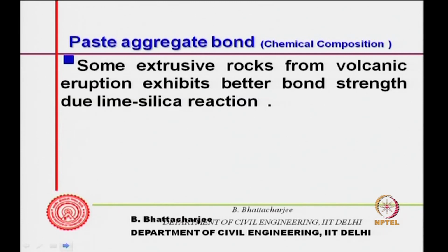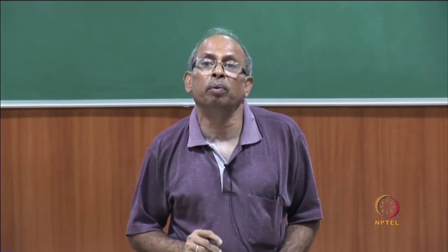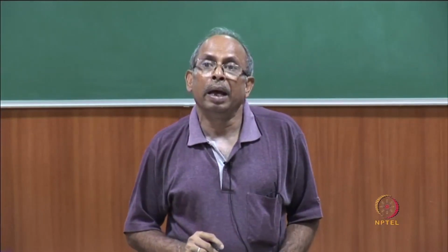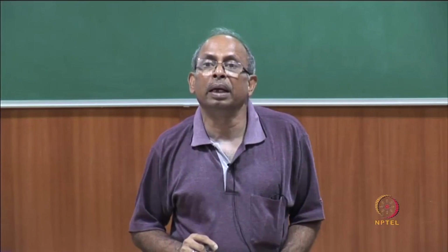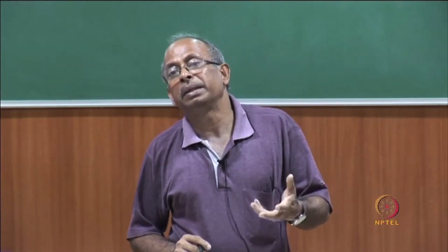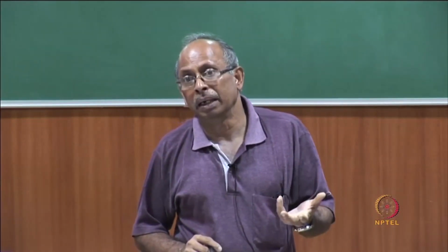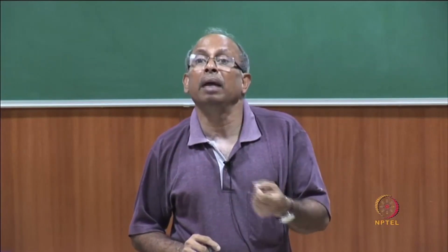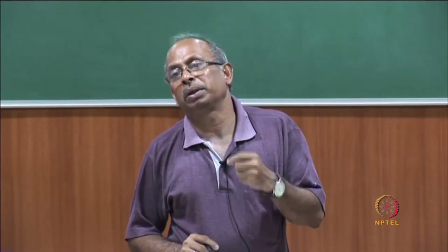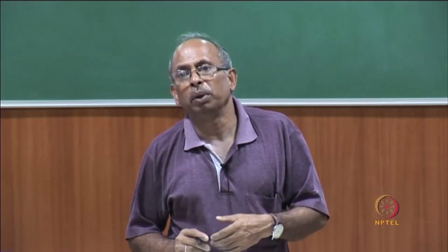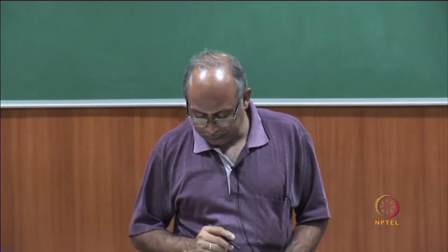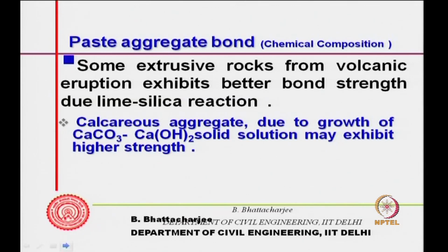Volcanic, as I said, the chemical bonding occurs when you have got volcanic extrusive rocks from volcanic eruption, and they can have better bond strength due to lime silica reaction, because cement hydrates have got lime, that is what we have seen earlier, and this lime can react if the aggregate surface has got some sort of reactive silica. So, something similar to pozzolanic reaction can occur.